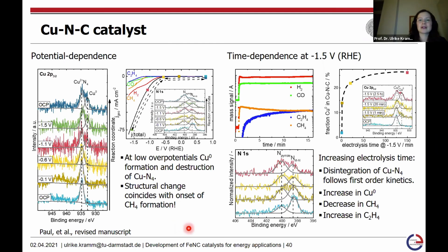We then also performed a time-dependent variation, and here we have the different products. So what you can see when you measure over a distinct time is that at a certain point, the formation of methane goes down, and you see even more ethylene within the product. Whereas the other products basically remain constant with respect to their intensity. And here is the fraction of the Cu0 state within the catalyst material as a function of the electrolysis time at a potential of -1.5. And what we can basically see is that we have some kind of first order kinetics for the disintegration of the Cu-N4 centers. And again, we can see that with an increase in the Cu0 state, we have a decrease.